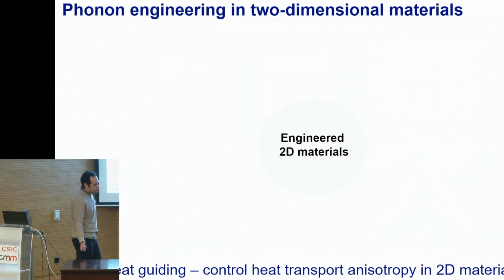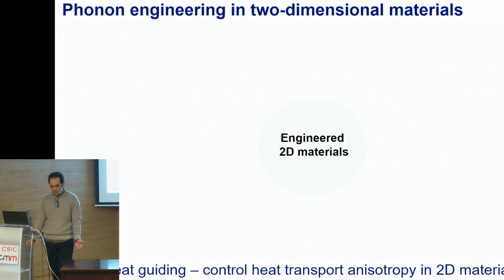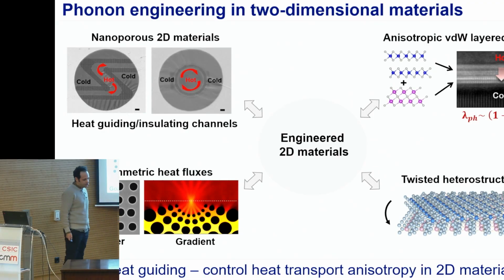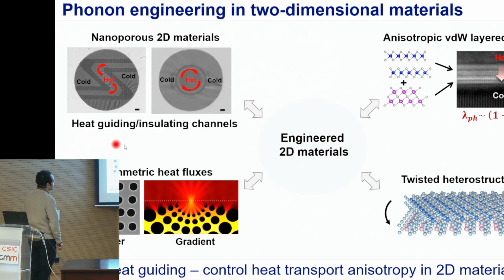The same thing we are doing also with 2D materials, and this is something that we did recently. So how we engineer these 2D materials: we are using nanopatterning to create nanoporous materials in order to create these heat guiding and insulating channels on top of the 2D materials. I will show you later on how we characterize these materials. We are using phononic crystals, disordered, and gradient structures in order to really guide the heat flow in specific directions.